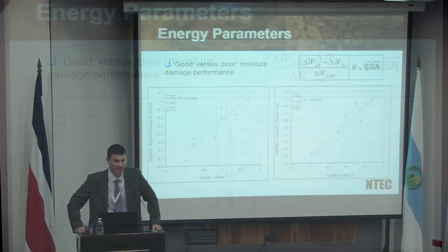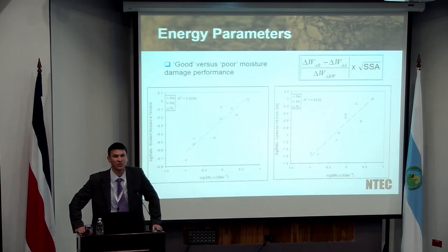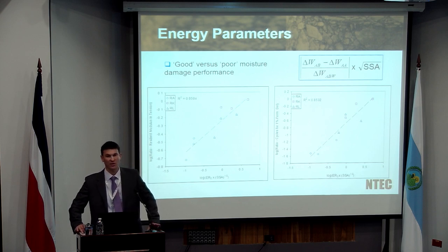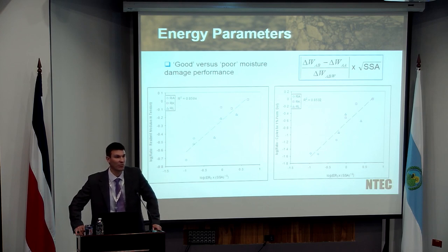The energy parameter that we used in this particular example was ER4, which was the adhesion minus the cohesive properties of the binder, divided by the wet adhesion, times the specific surface area. So that's good. Does it give us all the answers? And the problem was, it doesn't. It allows you initially to be very selective in terms of your components. But if you think back to the framework slide that I presented right at the beginning of the moisture damage section, component selection was only part of the equation.